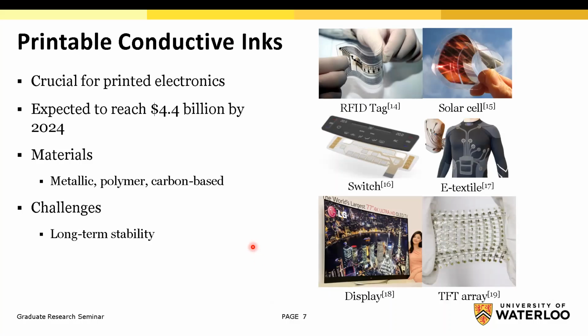These conductive inks are expected to reach a 4.4 billion market size by 2024. Here are some of the areas where printed conductive inks are used, like RFID tags, solar cells, switches, e-textiles, displays, and TFT arrays. Some of the materials that can be used are metallic, like silver, copper, or gold. But since silver has the highest conductivity, really good air stability, and lower cost than gold, silver is the main metallic choice. There are polymer and carbon-based materials as well, but even though they have really good mechanical properties, their conductivity and performance are really low. And the current challenge with conductive inks is long-term stability.